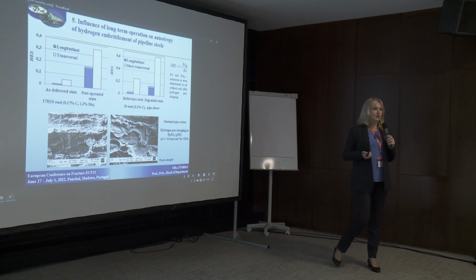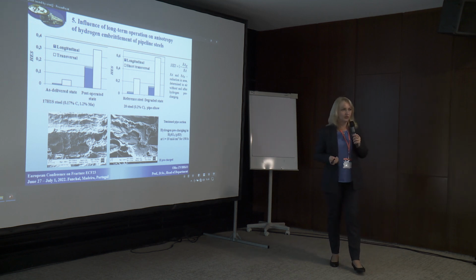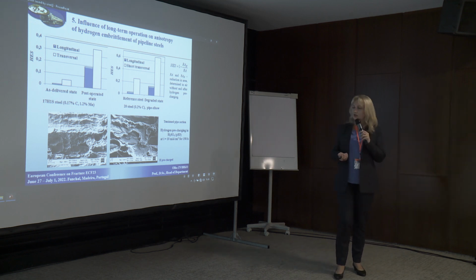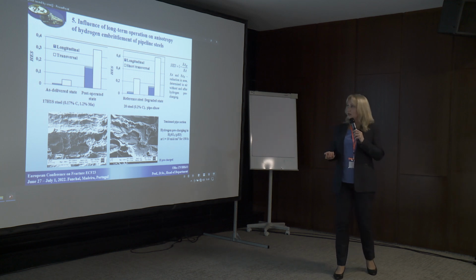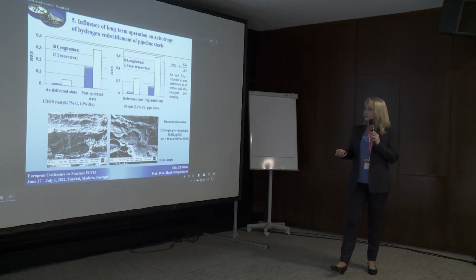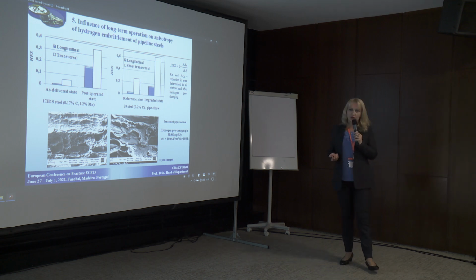And long-term operation influences anisotropy in hydrogen embrittlement susceptibility. And we can see that the metal of the tension section of the pipe elbow was characterized by higher sensitivity to hydrogen embrittlement, especially when testing short transversal specimens, and a similar tendency was observed for the low alloy steel.